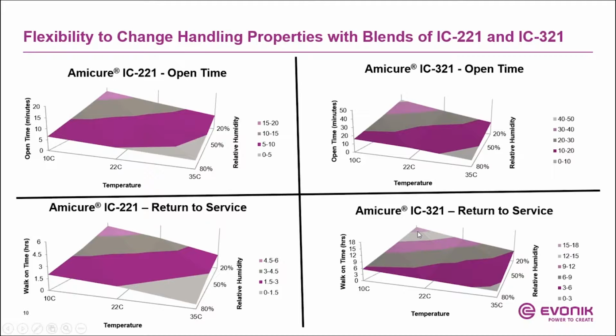If you're working at lower temperature, lower humidity, you do get the benefit of higher working time, but then return to service is a little slower. So in that case, you probably want to use 221. The key takeaway here is that you can blend these two curing agents together to get the balance of working time and return to service. A lot of times the customers will have multiple products, one for the winter season, one for the summer season, for that reason, because humidity and temperature do have an effect on the working time and return to service.